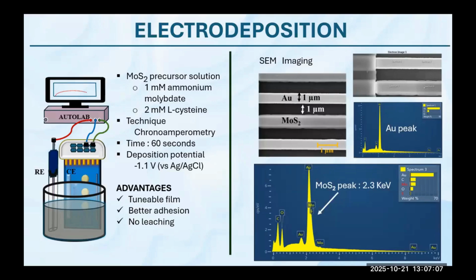As we can see here, this electrode is not affected, while this one seems to have undergone a slight change in the morphology. When we do the EDS analysis on this one, we see a sharp gold peak, so there's no other element deposited on it. While when we do the EDS on this one, we see a peak at 2.3 keV, which is well reported in literature to be the peak for MoS2.